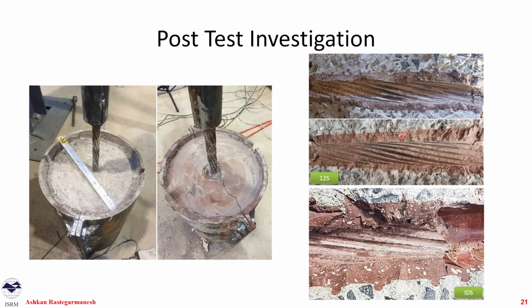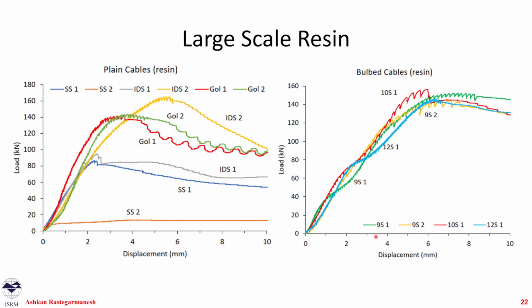After the test, we broke our samples. We studied the type of damage we get. We realized that uniformly throughout this whole PhD work, the damage tends to be non-uniform. So towards the exit point or towards the collar here on the right, we get lots of damage, a crater and dull edges. As we go towards the bottom section of our sample, we see very sharp edges and very, very little amount of damage. This is, for example, an indentation imprint on our grout, which you can actually see. So that means that it's actually something that's useful and it's working.